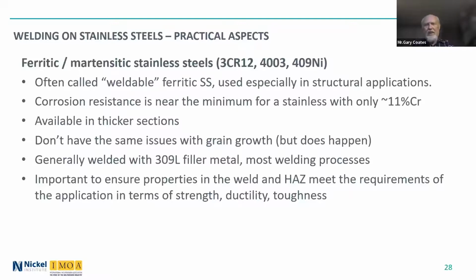I mentioned about the weldable ferritic stainless steels, which are actually ferritic martensitic grades. I know in India you're producing a number of them, and they do have their applications, and especially in structural applications where you can use the strength of them. And because they're lower alloyed, they're also lower cost. So they have resistance to inland atmospheric conditions, not near the sea where you have salt spray and chlorides present. So, as I say, the corrosion resistance is near the minimum for stainless steel.